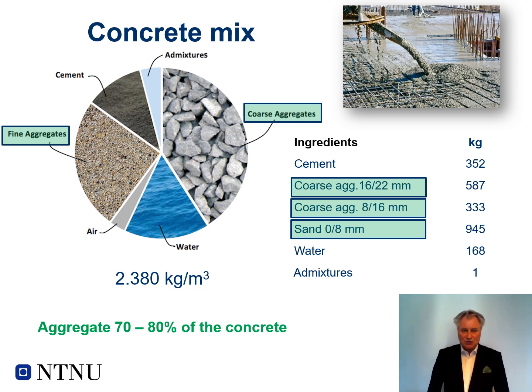Concrete, of course, is glued together with the aggregates, and the glue is the cement and the water. So a typical concrete mix could look something like this for 1 cubic meter. You have the cement, around 350 kilos. You could have a coarse aggregate, which could be a 16 to 22 millimeters particle size, almost 600 kilos. And you have the slightly finer coarse aggregate, 8 to 16 for instance, around 330 kilos. And then you have the sand fraction, which is a typical 0 to 8 millimeter, around 945 kilos. And then you add to the cement the water, so you will have a water-cement ratio, in this case around 168 kilos of water.